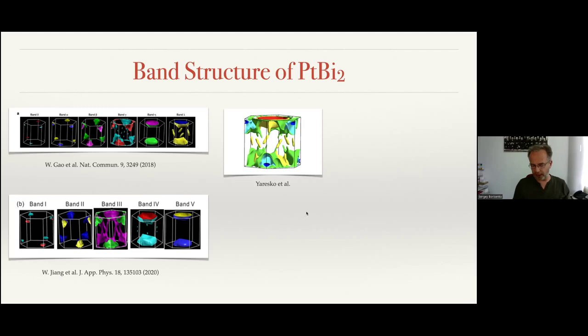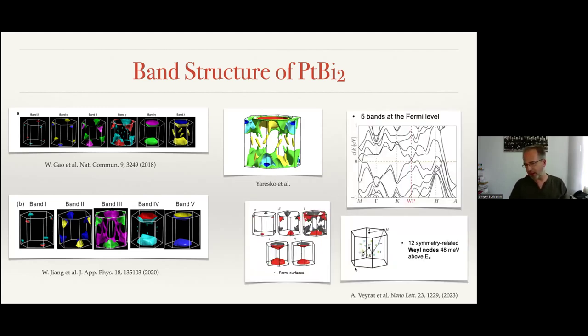In any case, this has been known earlier, and the renewed interest is because our colleagues, Jeroen and his colleagues from the Theory Institute in IFW, followed my experimental colleagues from the Institute for Solid State Research, who saw very interesting tunneling spectra and also transport properties. This was a joint effort of IFW researchers, and they found in particular that this is a Weyl semi-metal. Most of the Dirac Weyl semi-metals were known earlier, but this particular non-degenerate crossing of bands at a single point had not been noticed earlier. It is now a very interesting subject to study, and it turned out that platinum bismuth 2 has 12 symmetry-related Weyl nodes, located slightly above the Fermi level.